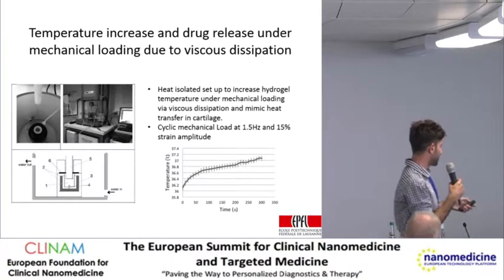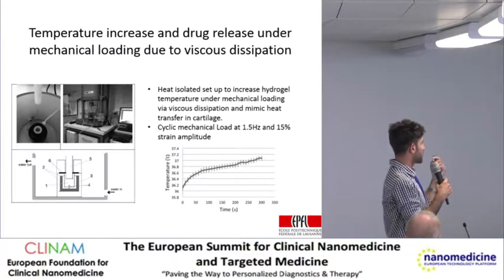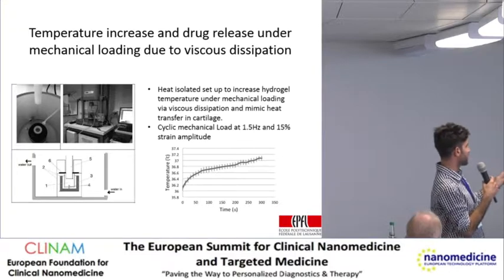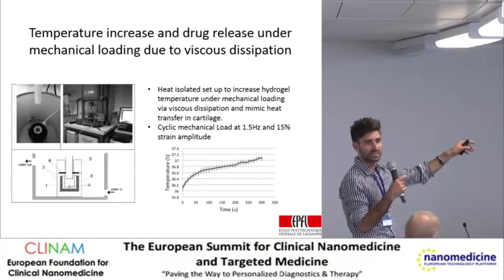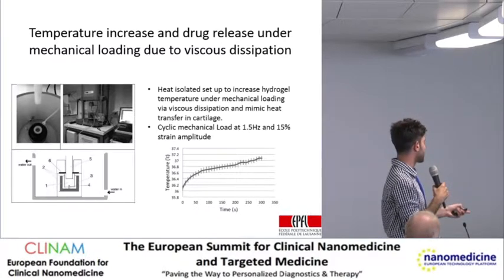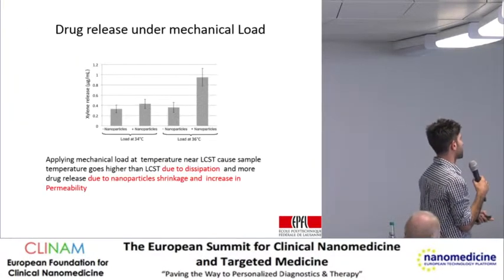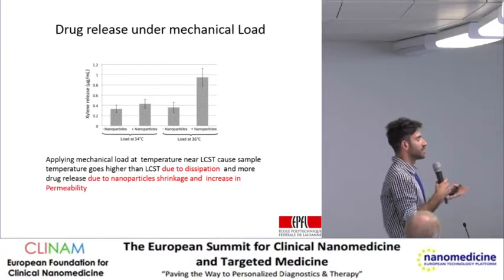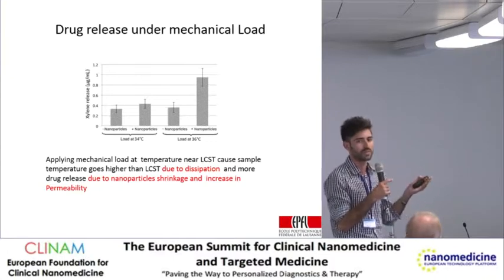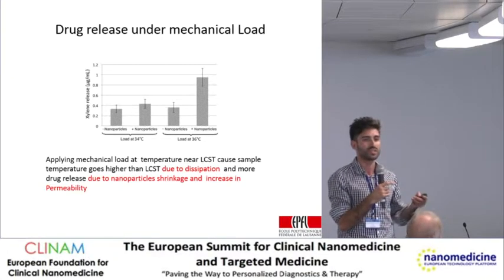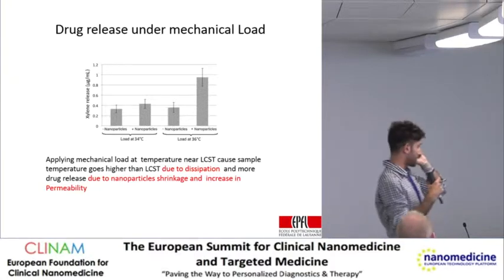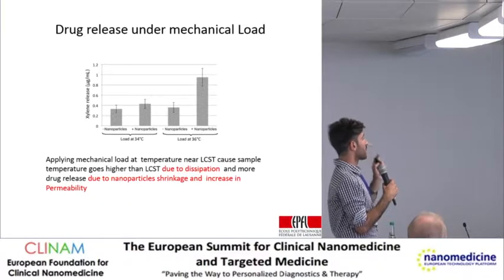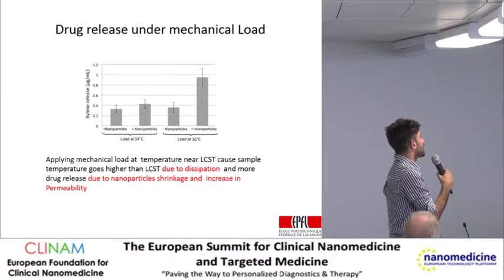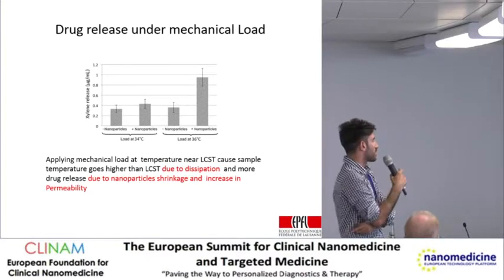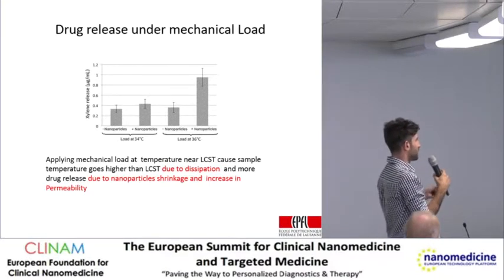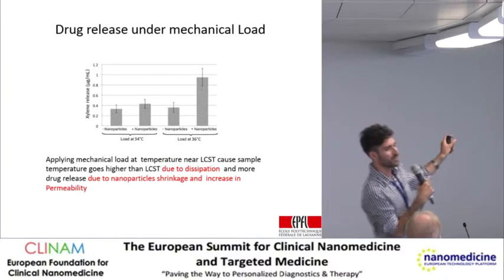And when you apply load on this material, and you set the environment temperature at 36, for example, after 5 minutes of loading the temperature can increase 1 degree and reach 37, which is required for the nanoparticles. And again, we had our 4 groups. Once we set the environment temperature at 34, we didn't have a significant difference between the 2 groups, because when you set it at 34 with loading, it never reached 37 with this system. But at 36, after 5 minutes of loading, we had much more release from the group with nanoparticles compared to without nanoparticles. That shows that here we could show the proof of concept of the figure that I showed first.